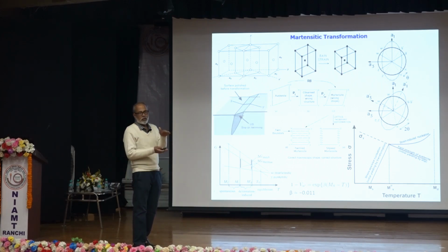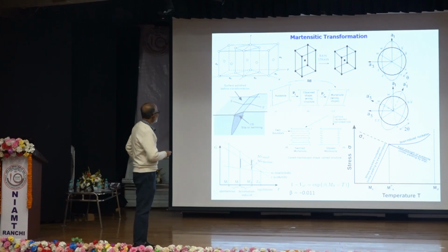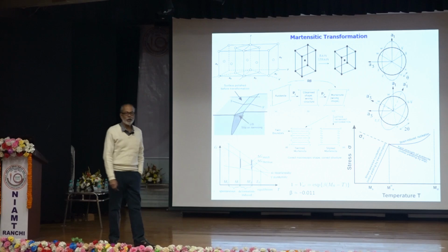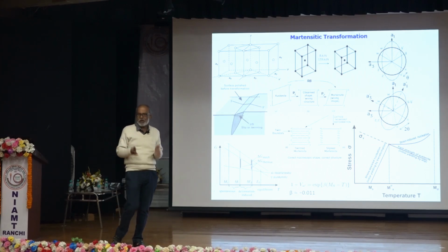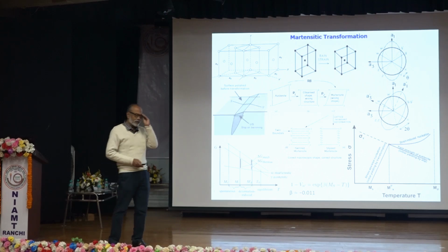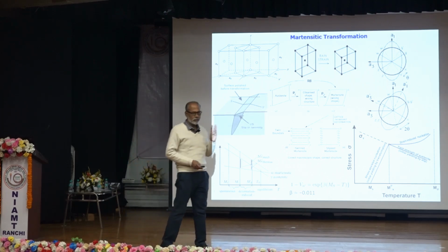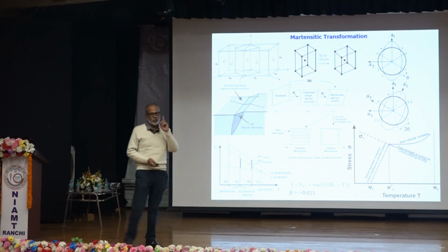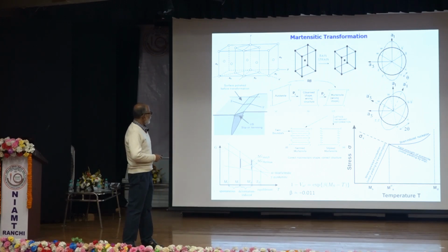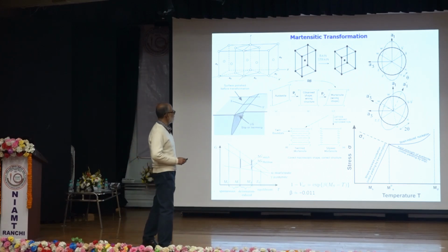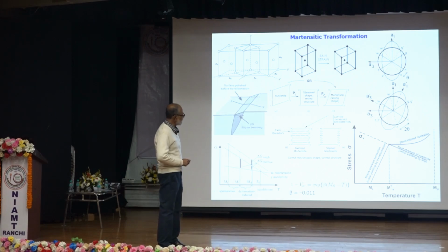And when this homogeneous shear occurs, you can guess an interface can be created between the two entities. There can be an interface because there is a shape change, right? So for martensitic transformation, two things we require. One is a change in crystal structure, whatever shear we apply, and second, a change in shape. But the transformation proceeds within the FCC. The BCC or BCT grows within the FCC. So there has to be some interface. What is the nature of the interface? So Bain proposed a model to conceive this kind of homogeneous shear.